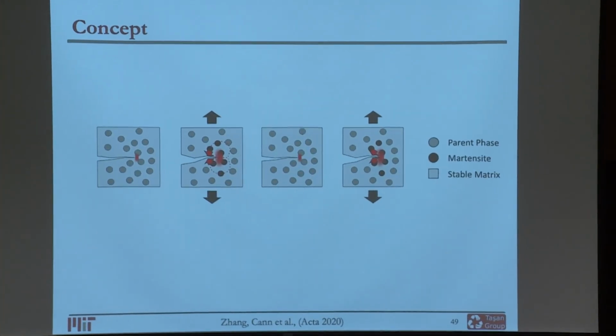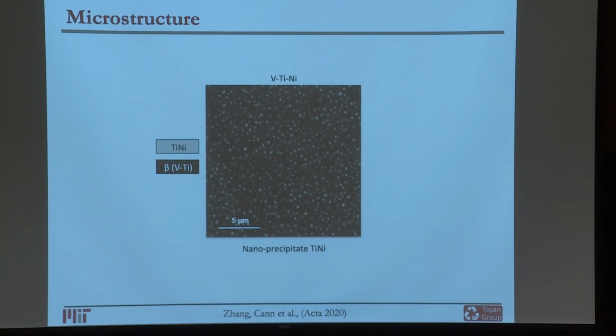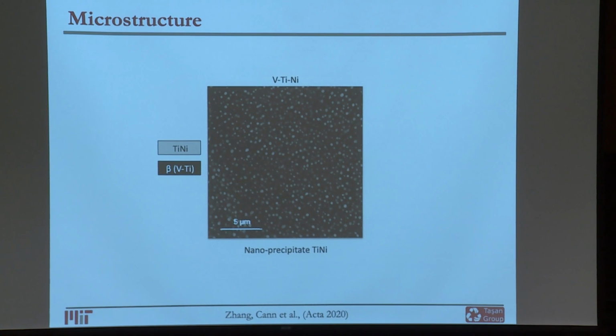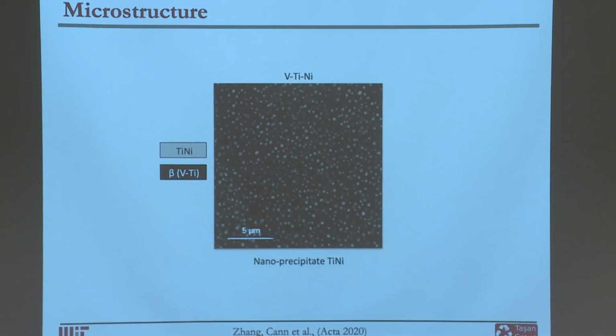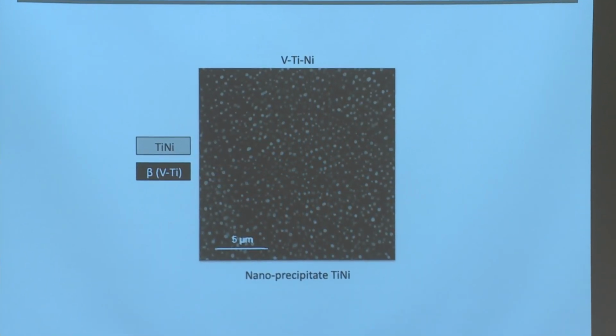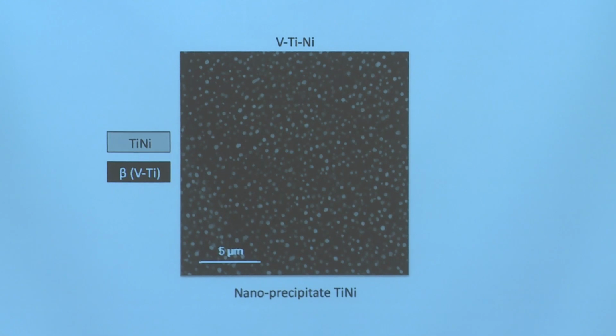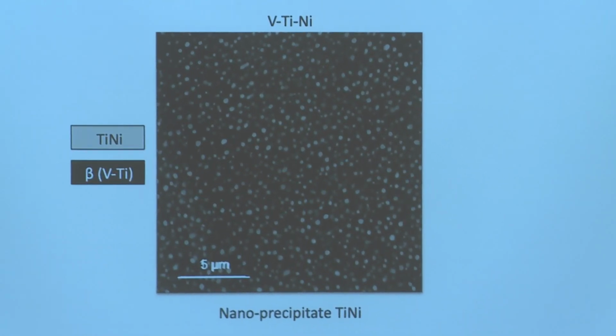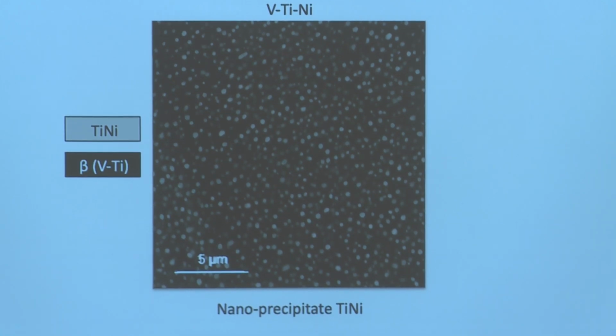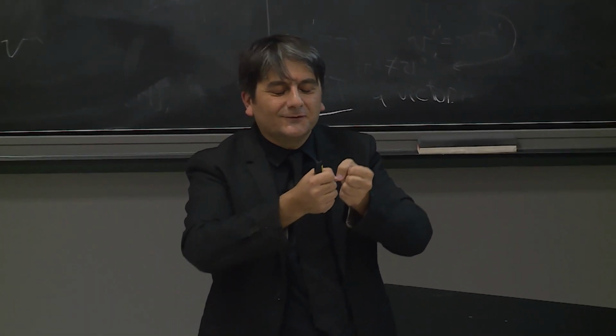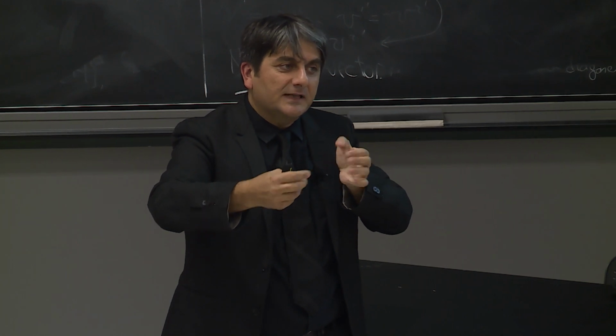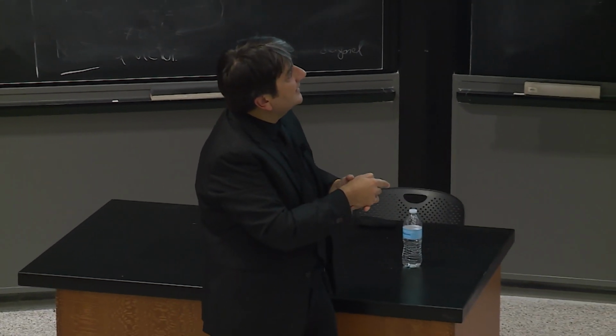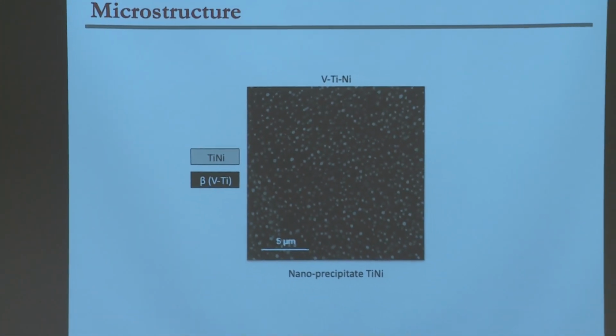So it's nice to make these cartoons, but can we actually make this kind of material? So this is a titanium nickel vanadium alloy that has this kind of microstructure. So titanium nickel is the most well-known and most commonly used shape memory alloy and also superelastic material. And what we really want to have here is a second phase that we can introduce in the material, which is essentially showing some superelasticity. With first deformation, you will have the forward transformation, and as you release the load, it's going to, by itself, transform back. So we tried to create this titanium nickel nanoprecipitates, which was successful in vanadium titanium nickel system.